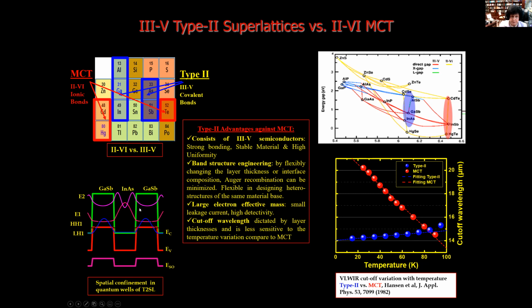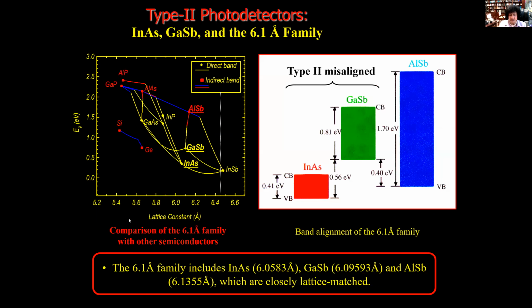And now another part is, thanks to the type-II, we have the separation of electron and hole, and by changing one monolayer, we can change the wavelength at the same time, but with the same effective mass. The large effective mass gives much less dark current, and especially at the long wavelength, much better performance. So all of that is the many advantages of the III-V and the type-II by comparison to mercury cadmium telluride.